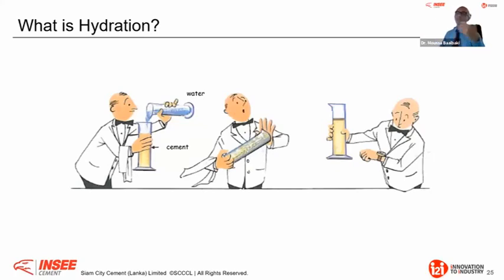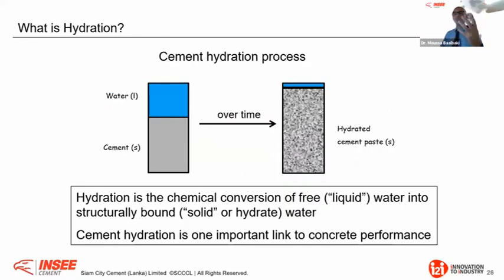Now, when it comes to hydration, what we do first, we have your cement, you have your water, okay? Therefore, over time when you mix them, you produce what we call a hydrated cement paste. And you have a certain, let's say, porosity. This is water, okay? When this water dries up, you will have a certain porosity. But within the cement hydrated phase, you have pores. These are small pores.